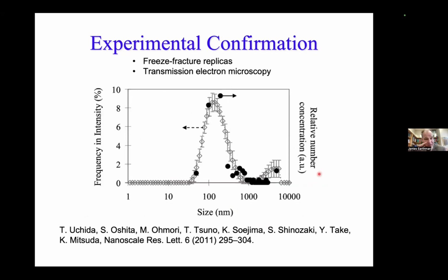Then we found another paper. This is by another group in Japan, a different group. They created nanobubbles the same way with a large distribution of microbubbles. But in this case, instead of measuring using a light scattering technique, they used freeze fracture replicas. And freeze fracture replicas are really difficult to make. You have to have a very expensive machine to make them. But basically, what is done is you freeze a droplet with, in this case, nanobubbles in it, instantly inside this machine. And while the droplet is frozen, a wedge comes in, fractures the droplet, and then replica films are made on the fracture surfaces of that droplet.